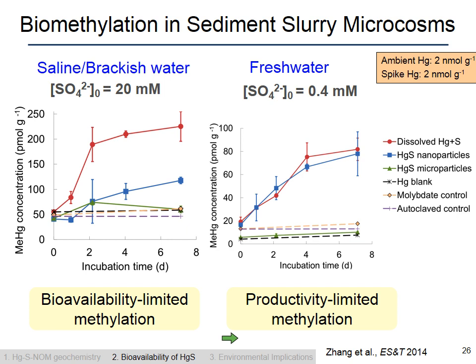But what we think is going on between this freshwater and saline water is that you have different things that are controlling methylmercury production in these microcosms. On the left, you have methylation that's limited by the bioavailability of the mercury, and hence you get the differentiation between dissolved and nanoparticles. On the right, what we see is no differentiation between the dissolved and nanoparticles, but also a lower sulfate concentration, which we think means that in this microcosm, methylmercury production is limited by the productivity of the organisms that produce methylmercury. And these organisms, as I mentioned before, are anaerobic organisms, including sulfate reducers. So here with the lower sulfate, we probably have what I call microbial productivity limited methylation.